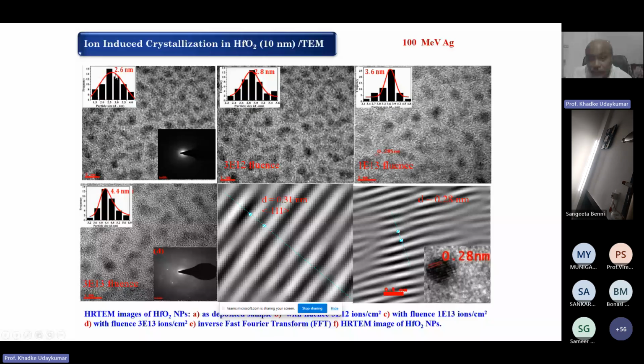Further increase, going up to 10 to the power 13 fluence, you are seeing that the particle size is increasing up to 3.6 nanometer. When you increase to 3 into 10 to the power 13, again it is increasing. So the particle size is increasing. Now let us see what is happening inside, in this particular diagram.